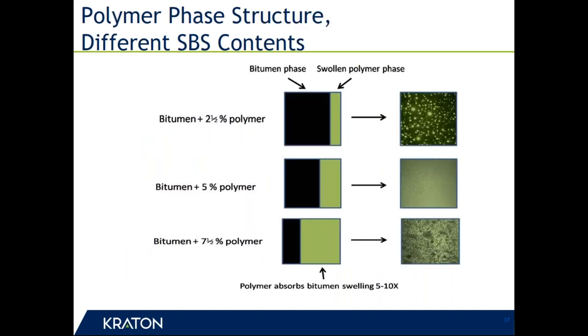Now, where are things going from here? Looking at what happens when you add polymer to asphalt, we mentioned that you could almost call it a digestion sort of thing. At any rate, you have two phases within the binder. You have an asphalt phase, or bitumen phase, as it's called here. And the polymer will actually absorb part of the chemical component of the asphalt binder and swell up. So that's why you see this depiction here. There's 2%, 2.5% by weight, but the volume winds up being higher than that after everything is said and done. On the right-hand side, you can see what looks like little stars or little blocks of polymer that are suspended in the asphalt binder. Down here, you've got little balls of asphalt binder suspended in the polymer, where the polymer is really controlling the entire response mechanism of that binder.